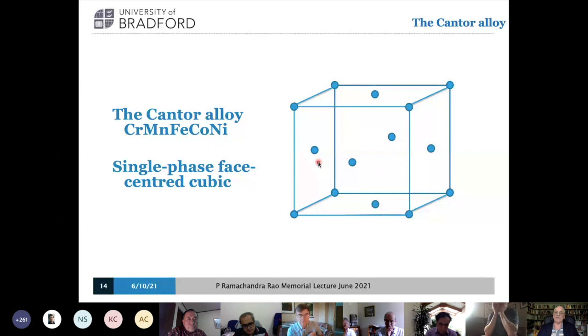And nobody would have predicted it because of these five components, nickel is the only one that's face-centered cubic, has this structure at room temperature. And in general, we don't get such extended alloying with a single structure. We now know that actually in multi-component phase space, in multi-component materials, there are literally massive amounts of single phase fields. There's an enormous number of single phase face-centered cubic materials, and there's an enormous area of single phase body-centered cubic materials, and every single crystal structure we know about has an enormous sea of multi-component solution region where the atoms are randomly distributed across the structure in the way I've described for the Cantor alloy. But this was the first one that was discovered, and it was really quite a shock.